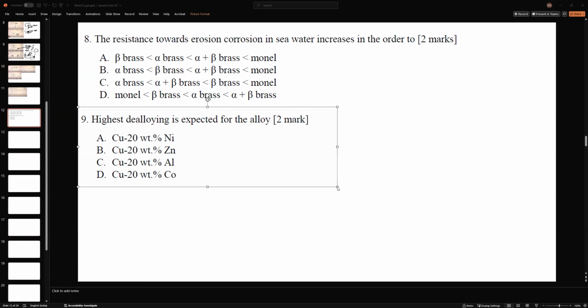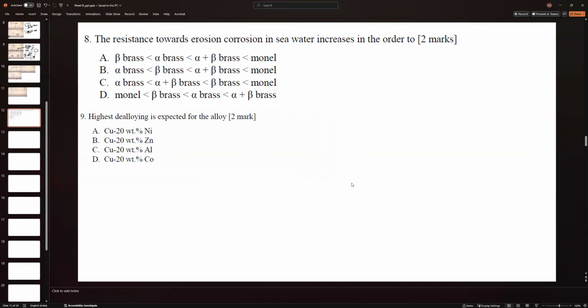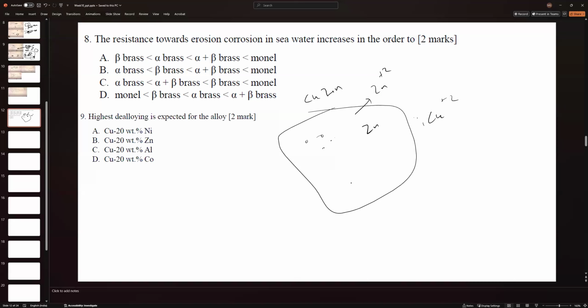What is happening in dealloying? You have your sample which has both copper and, suppose, zinc. When it's exposed to the environment, your zinc atoms would leach out as zinc plus 2, and your solution has some copper plus 2. So this zinc would give its electron to this copper, and so copper would get deposited somewhere, and zinc would leave, forming pits on the surface.